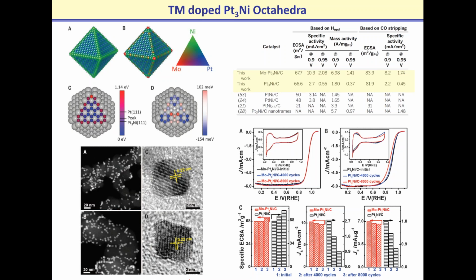So they were able to produce platinum nickel octahedrons, and they also introduced moly as an ingredient, like a ternary alloy, and they do claim that the introduction of moly substantially improved activity, and they were able to reach pretty high values for both specific and mass activity. And again, here we're looking at numbers that were obtained in RDE, not MEA.